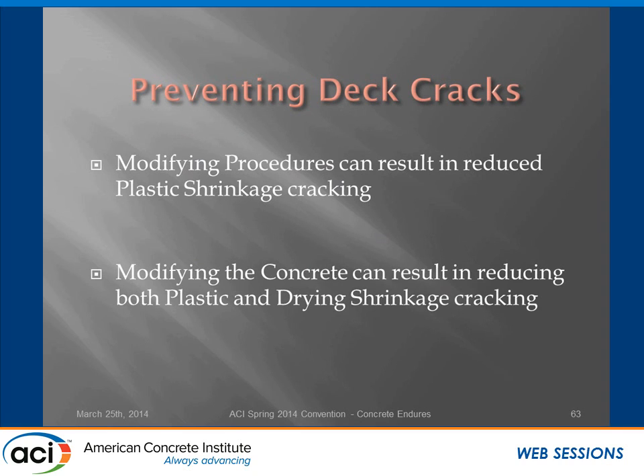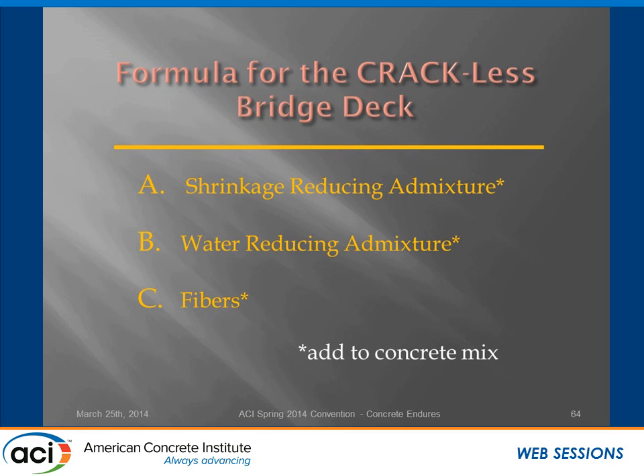Well, there's two ways to go about it. One is to modify the procedures, and that can help you reduce plastic shrinkage. And you can also modify the material, the concrete itself, and that's going to help you with both the plastic and the longer-term drying shrinkage. So here's the formula that we came up with to have crackless bridge decks. It's pretty simple. We have ABC: shrinkage-reducing admixture, water-reducing admixture, and fibers. And if there's any contractors in the room, we add that to the concrete mix.